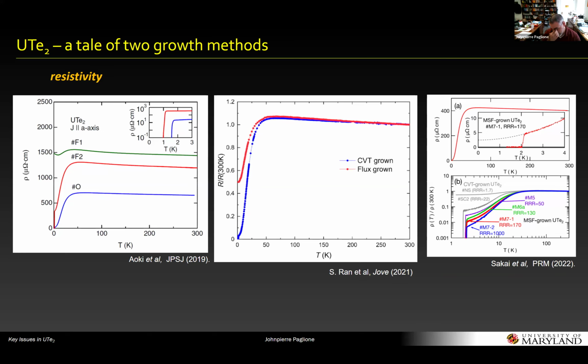And as has been mentioned by many people, I think it's probably due to the vacancy count of uranium. That's the likely culprit, but it's at the less than percent level. It's a very small effect. And to this day, I'm not aware of a very in-depth or systematic study that's characterized that systematically to show that the count of uranium vacancies corresponds systematically to some property. There's indirect studies, of course, and I'll touch on this. Okay.